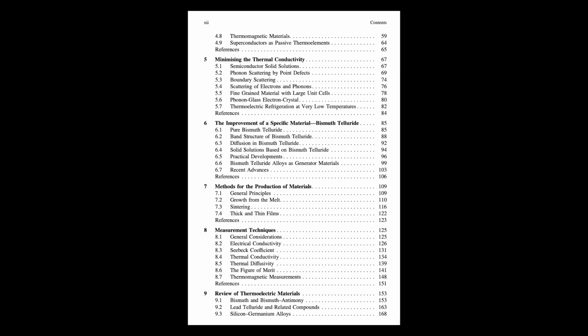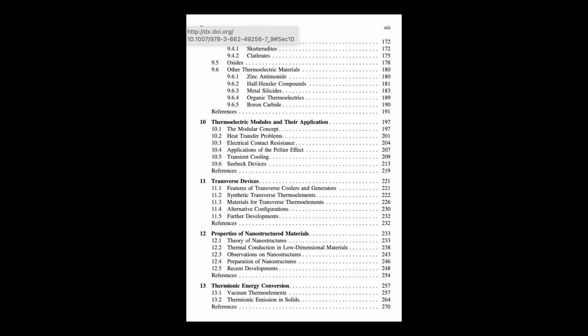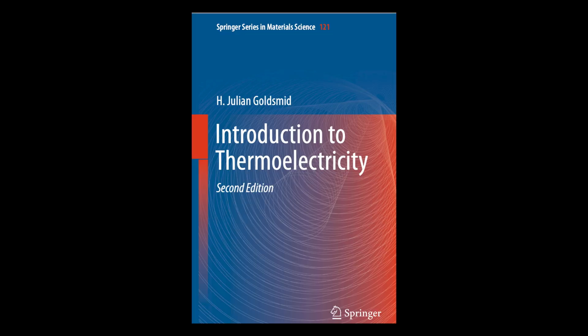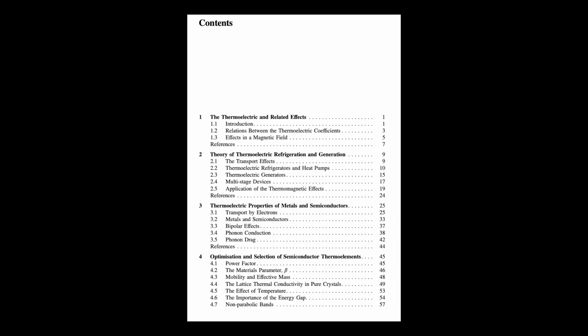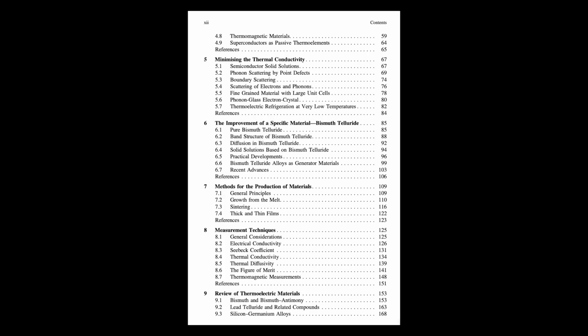Fascinating. Okay, let's switch gears to strategies for minimizing that unwanted thermal conductivity. First up, solid solutions. What are they? How do they trap heat? A solid solution is basically an alloy, mixing two or more semiconductors with similar crystal structures. Think Bi2Te3 mixed with Sb2Te3. The idea, championed by Ioffe way back, is that this atomic mixing creates disorder in the lattice. This disorder acts like speed bumps, scattering the short wavelength phonons that carry most of the heat. But, and this is key, the longer wavelength electrons carrying the electricity might pass through relatively easily. So you knock down the lattice thermal conductivity without hurting the electrical conductivity too much, hopefully. Examples like Bi2Te3-Sb2Te3 for p-type and Bi2Te3-Bi2Se3 for n-type are classic examples, still widely used. So a bumpy road for heat, smoother highway for electricity.